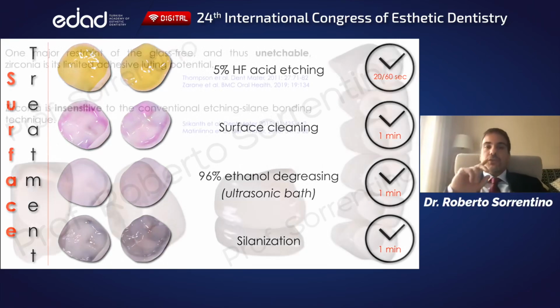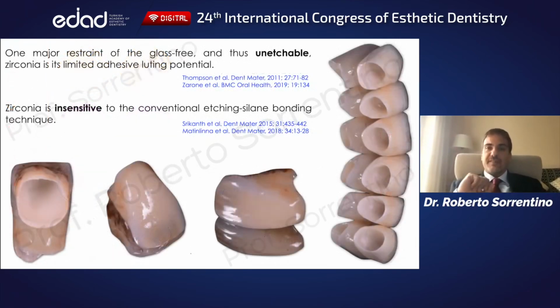However, this approach cannot be used with polycrystalline ceramics, just like zirconia and alumina, since they are acid resistant and insensitive to the etching and silane bonding technique. As a consequence, they cannot take, to date, full advantage from the conventional adhesive procedures, although the scenario is changing over time.